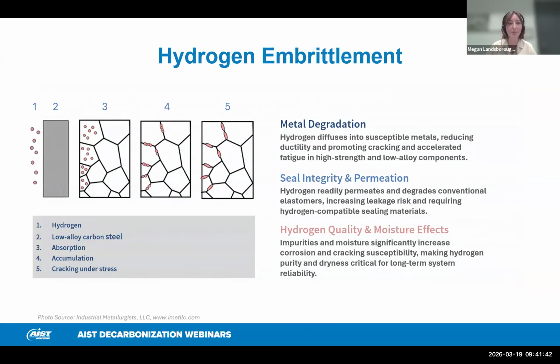Okay, perfect. Jumping into hydrogen embrittlement, the things I want to touch on include metal degradation, seal integrity, and hydrogen quality. So hydrogen diffuses into susceptible metals, reducing ductility and promoting cracking and accelerated fatigue in high strength and low alloy components. Hydrogen readily permeates and degrades conventional elastomers, increasing leakage risks and requiring hydrogen-compatible sealing materials. Impurities and moisture significantly increase corrosion and cracking susceptibility, making hydrogen purity and dryness critical for long-term system reliability.